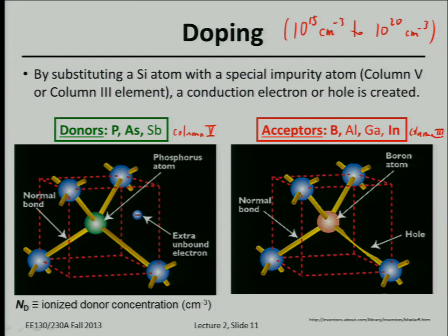So semiconductor manufacturing is a highly precise process. You have to be able to control impurities to a level less than 1 part per million, typically even down to 10 parts per billion. So that's one reason why it's expensive to build a manufacturing facility, because you need to be able to control contamination, or avoid contamination, very, very strictly.